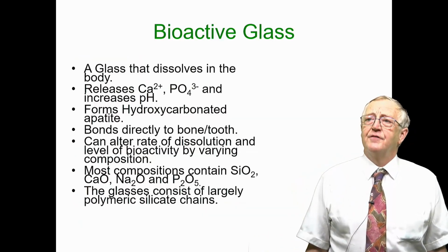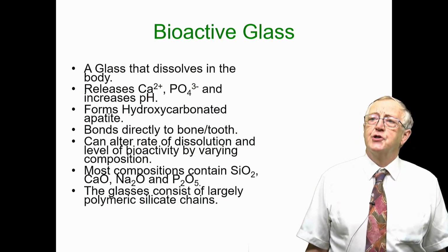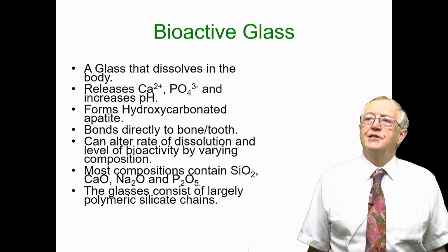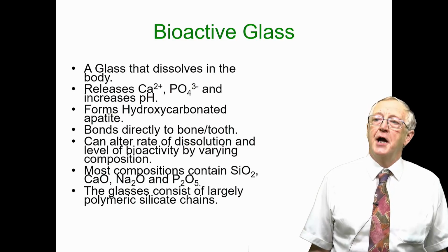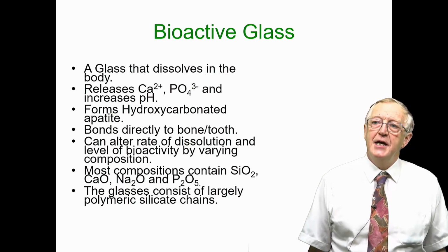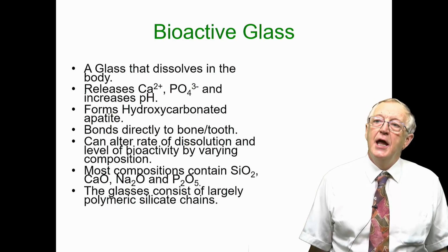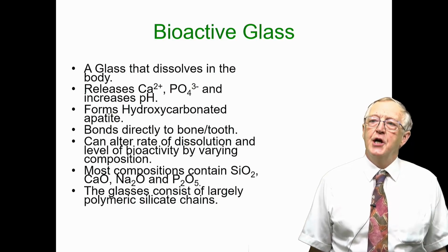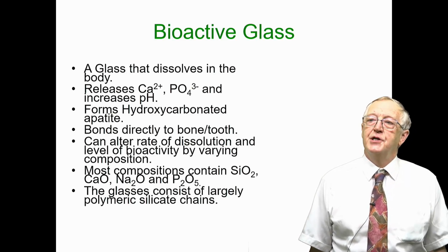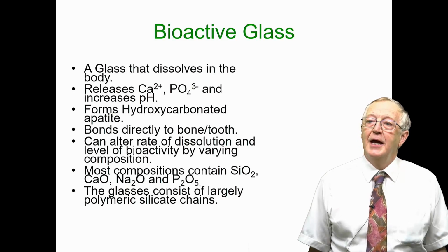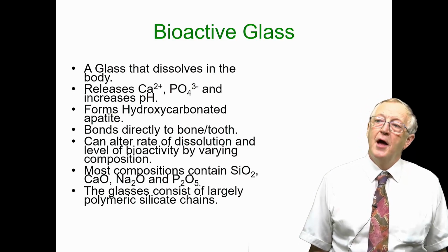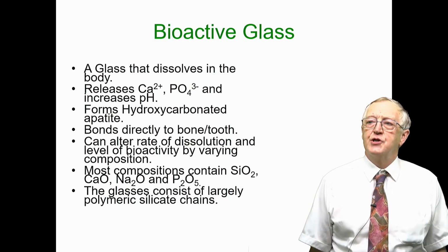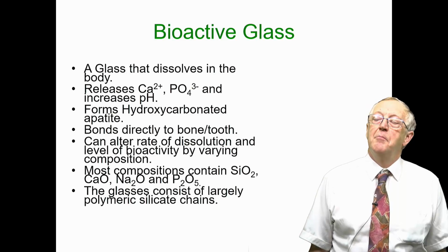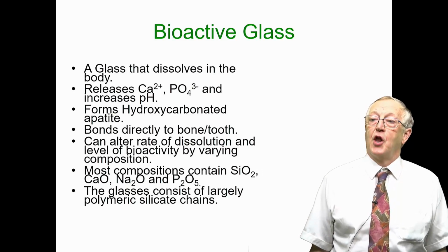So a bioactive glass is a glass that dissolves in the body. It releases calcium and phosphate ions, and as it does so, it increases the pH. It forms hydroxycarbonated apatite, the same mineral phase that comprises tooth enamel. It will bond directly to bone and tooth, and you can change the rate at which the glass dissolves and the level of apatite it forms by varying the chemical composition of the glass.